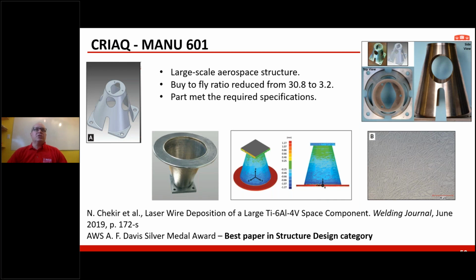That we have published. So the first one here originates from a CRIAQ program a couple of years ago. This is a large-scale aerospace structure that you can see here. You have the CAD model on the left, and the final 3D printed model on the top right of the slide. So we fabricated the entire component. This was qualified from TRL2 to TRL7-8. I would say the part met the specification and was ready to launch.